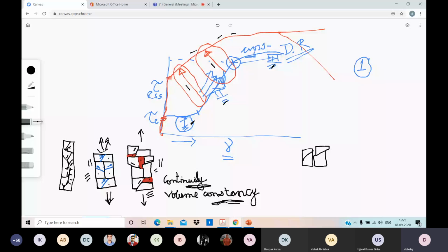That means if the dislocation movement is not through and through, then also there will be slip. In that case, the slip is partial. It may happen that a dislocation moves partially, say it was here and it moves to here. You will find not a full Burgers vector slip, but a little bit of slip.